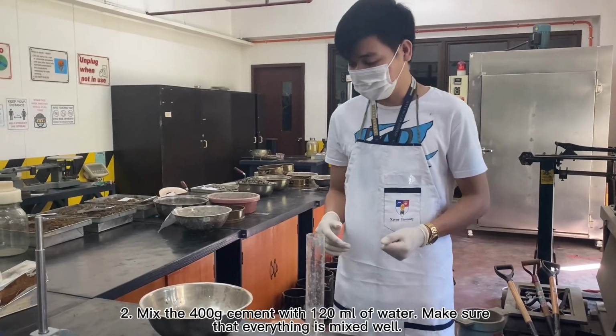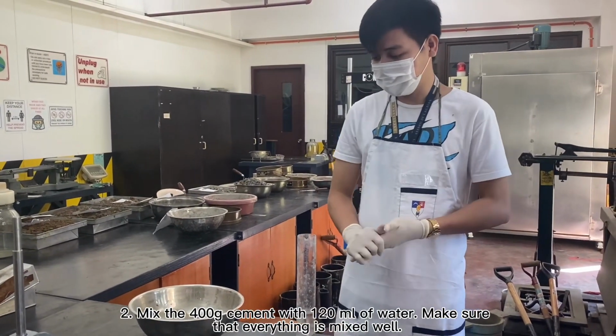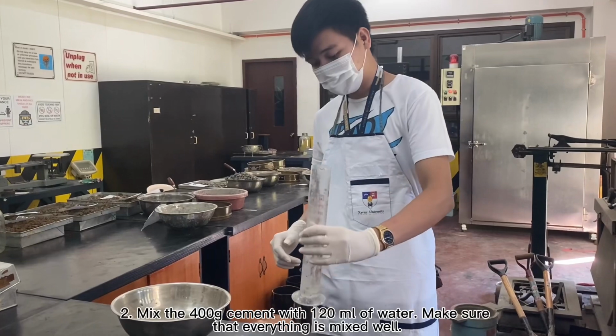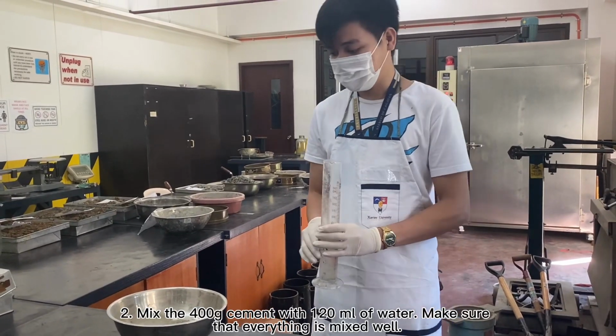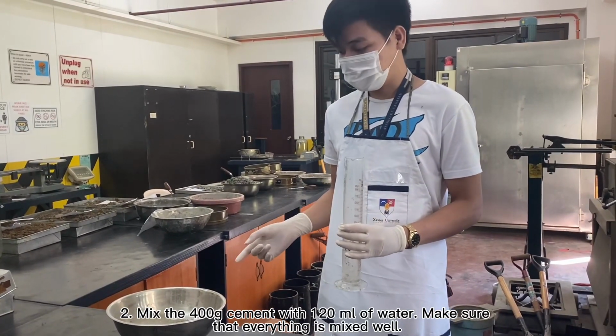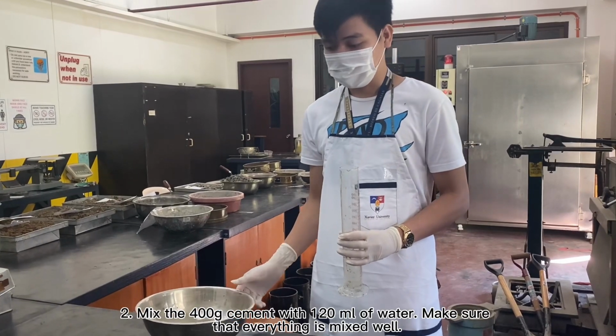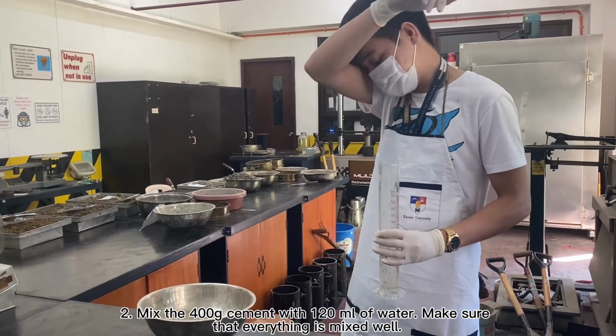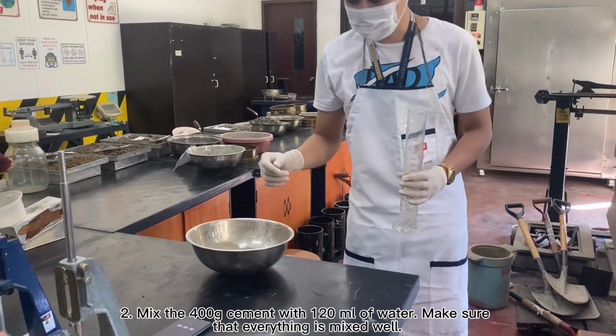So now we're going to start mixing the cement. We will add 120 ml of water to the cement, which is 30% of the total weight of the cement. And before mixing, we should start the timer.